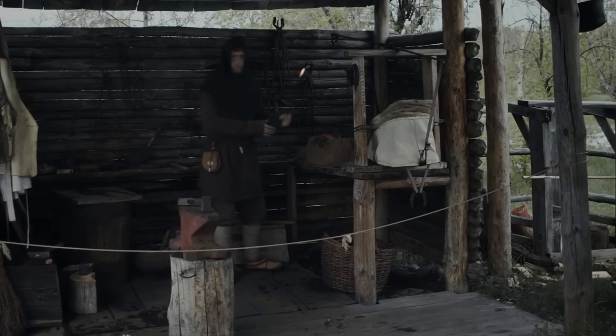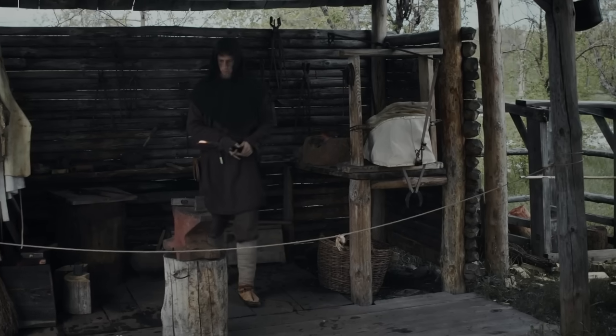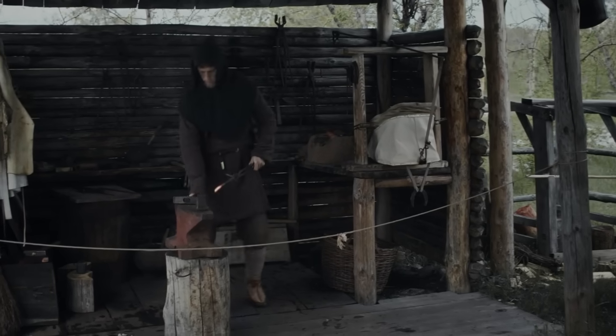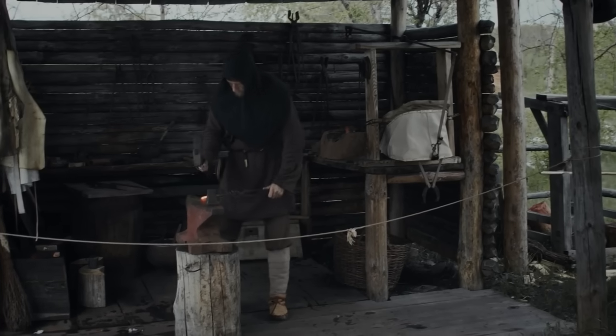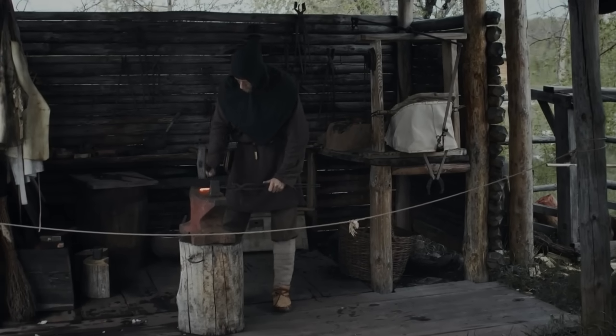After hardening steel in a quench, medieval smiths performed another critical step, tempering. They would gently reheat the blade and watch colours spread across the polished surface. Pale straw yellow, deep bronze, peacock blue, purple. These colours were not decoration. They were an exquisitely precise temperature gauge, caused by the thickness of oxide layers forming on the steel surface. Each colour corresponded to a specific temperature, and each temperature produced different material properties.